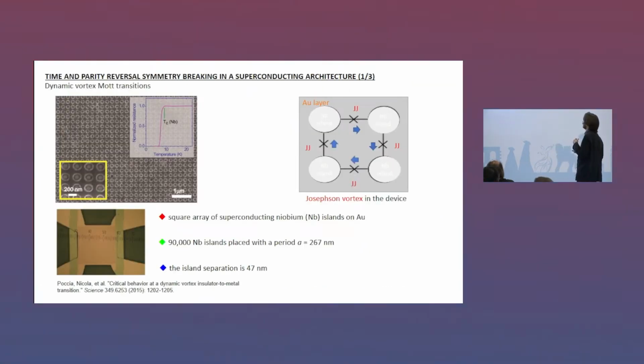So now, even if you use a single superconductor, like a conventional niobium structure, depending on how you realize the architecture, you can get a very exotic state. So the architecture and geometry are fundamental. In this case, what you see is 90,000 Josephson junctions organized in a square lattice of proximity superconducting islands on top of a gold substrate. What happens if you apply a magnetic field perpendicular to this kind of system is that you form a Josephson vortex, which you see on the right, which will start to move in one direction across the islands.